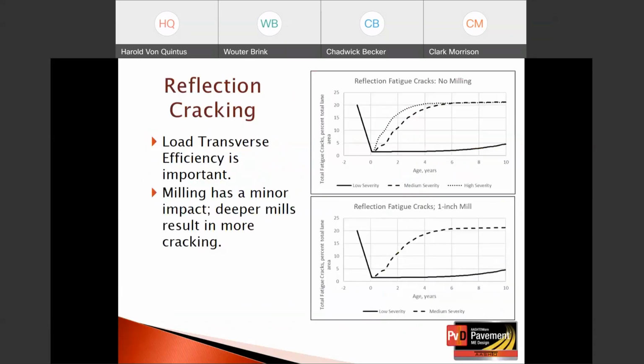This now shows another example. The example on the top is no milling. The graph on the bottom is 1-inch mill. And this is for reflective fatigue cracks, or reflective bottom-up fatigue cracks. Load transfer is important, and really milling only has a minor impact.